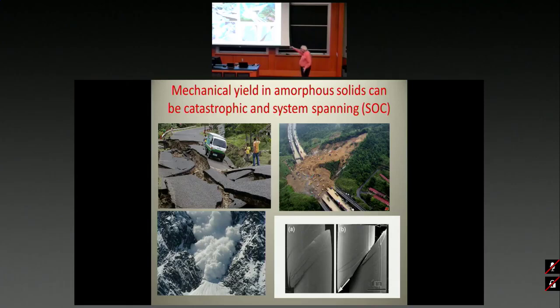Great. So if you take a rod of metallic glass and you uniaxially stress it, at some point it fails by creating what is known as a shear band. So you put a uniform shear or a uniform strain, and at some point, miraculously, all this uniform strain is localized in one plane, and at that point, the thing breaks. And the question is why? How can we understand it? What is the reason for finding a phenomenon now that goes over the whole scale of the system here? You also may notice that the shear band is at 45 degrees from the uniaxial strain, and this is also something we like to understand, why it forms in a way like this, etc.